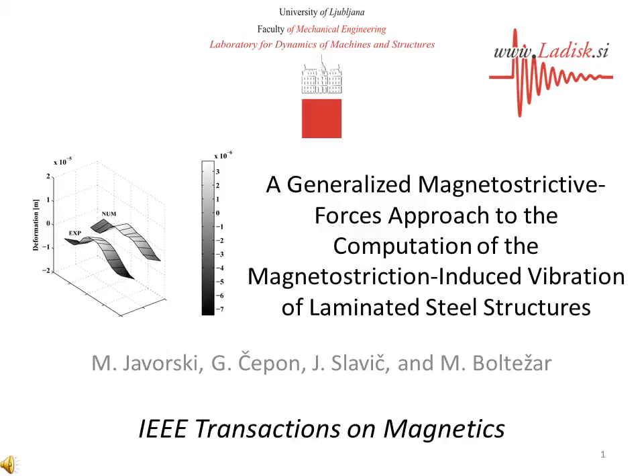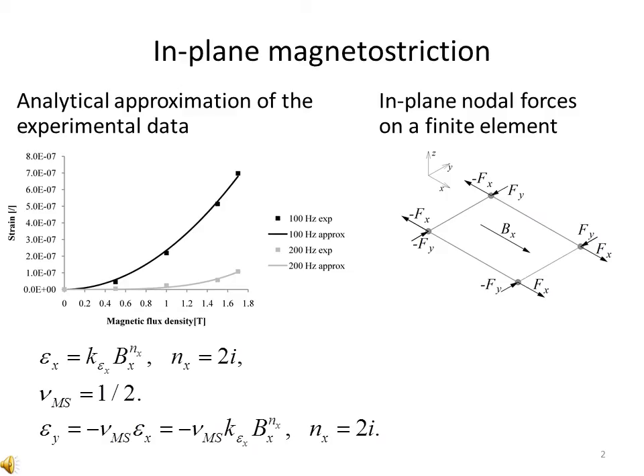The focus is on the in-plane magnetostriction of electrical steel and its transmission into the out-of-plane direction, in which laminated structures — e.g. transformer cores, stators and rotors — exhibit the greatest vibration. The in-plane magnetostriction model is based on experimental data acquired using the experimental method presented in the preceding research titled 'Frequency Characteristics of Magnetostriction in Electrical Steel Related to the Structural Vibrations,' published in IEEE Transactions on Magnetics in 2012. Each magnetostriction harmonic is regarded individually by introducing a power-approximative law with even powers.